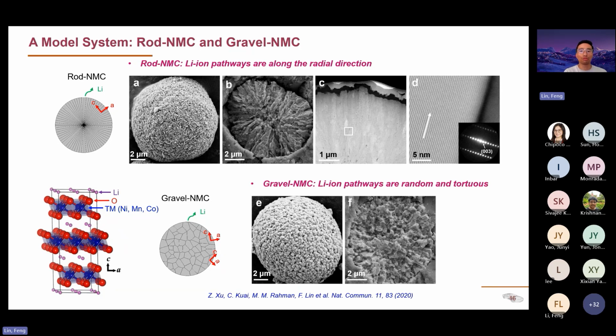With microstructural control, you can get two different materials with identical composition but different microstructure. This is really where material science can play an important role. Chemistry is mostly about chemical composition design, doping and coating and all those kinds of processes to improve materials. We found that if we use material science principles, just by controlling the grain microstructure and the grain morphology, you can get the same chemical composition and they will behave totally differently.